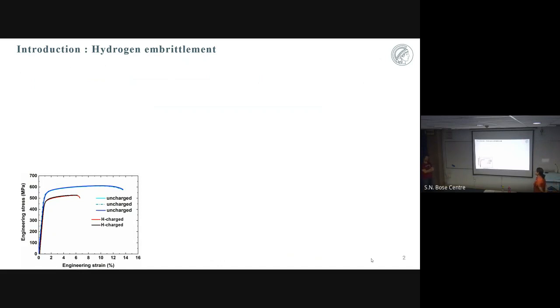But I felt like this is the reason why we should be interested in hydrogen charging of alloys and then study the further microstructure evolution. Since it affects so much, yes, here the effect is seen in ductility, not further. But since there is so much effect on the mechanical properties, this is what motivates us to charge it with hydrogen and see what is happening at the microstructure level. And therefore, we focus on the microstructural evolution once the material is damaged, because we are focusing on this part.